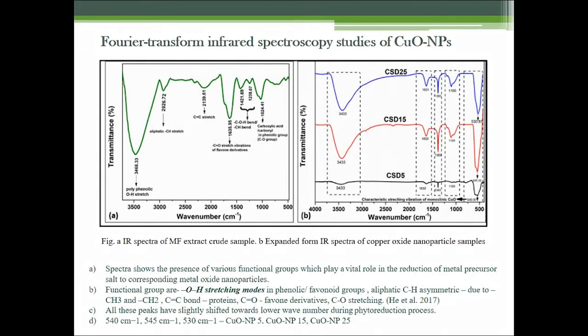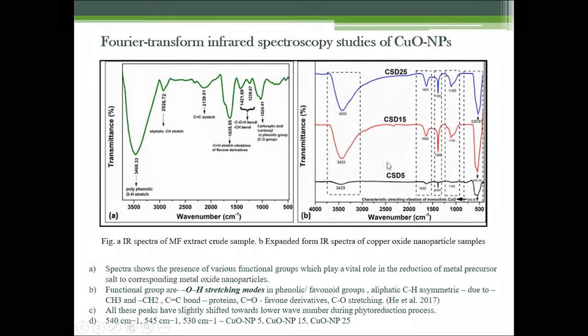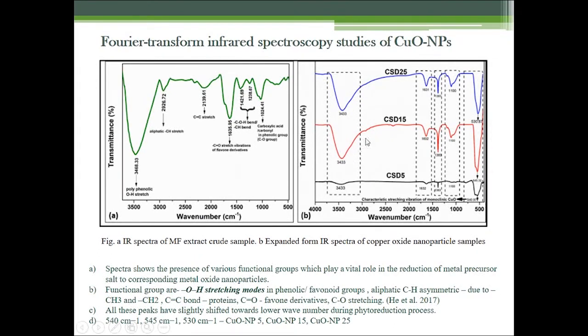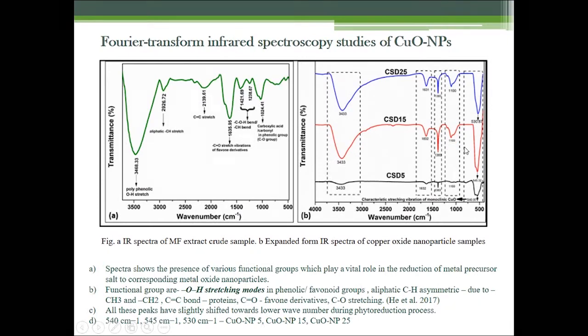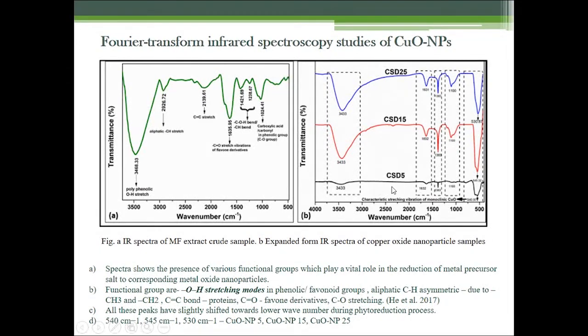proteins, and other phytochemicals. Similarly, here we have observed a small shift in the observed peaks in the copper oxide nanoparticles IR spectra. These peaks correspond to the phytochemicals which were responsible for the capping of the nanoparticles synthesized, and the strong peak which is present at the wave number around 540, 545 and 530 centimeter inverse is because of the formation of copper oxide nanoparticle.